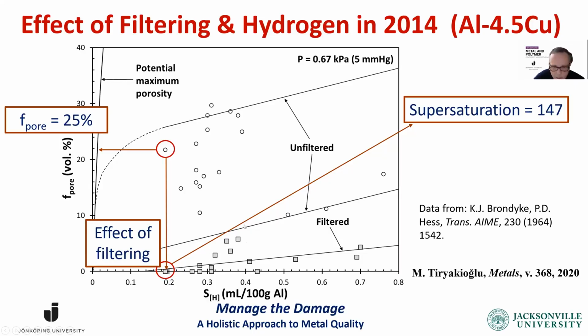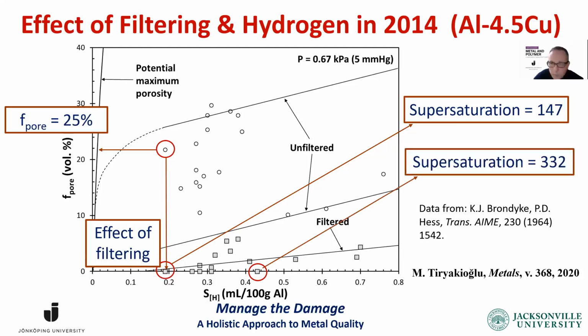Well, that's not all. There is one more point, and it's this one. It's again lying on the x-axis. And when I did the math, the supersaturation is 332. The metal had 332 times the hydrogen it was supposed to hold in equilibrium, and still no pores formed. There cannot be any more convincing evidence than this, that hydrogen by itself is not damaging.